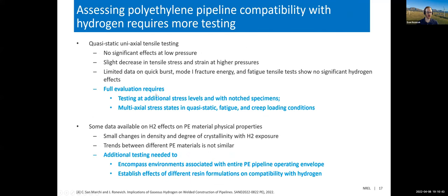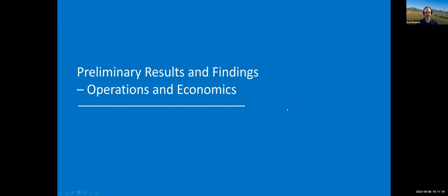Now on the polymer side, there's been some testing performed of structural properties, which generally has found no significant effects at low pressure, but really there needs to be more thorough evaluation of that. There's also been some testing that suggests that hydrogen can change the density and degree of crystallinity of some of these materials, but the extent to which that affects mechanical properties is unknown, and the trends are often different for different polyethylene materials. So again, more testing is needed here for us to be able to definitively say what the impacts of hydrogen on these materials are.